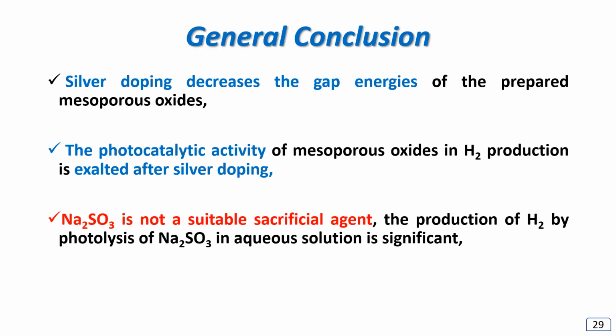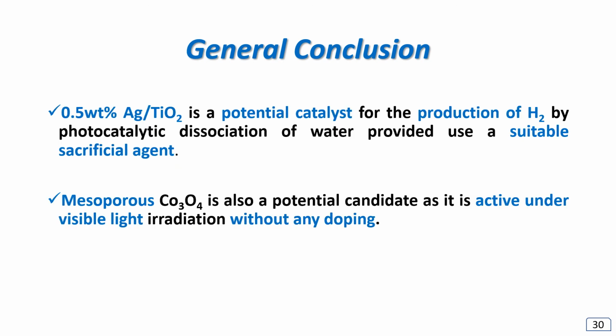In general conclusion, silver doping decreases the gap energies of the prepared mesoporous oxides. The photocatalytic activity of mesoporous oxides in hydrogen production is exalted after silver doping. Na2SO3 is not a suitable sacrificial agent. The production of hydrogen by photolysis of Na2SO3 in aqueous solution is significant. 0.5% Ag on titania is a potential catalyst for the production of hydrogen by photocatalytic dissociation of water, provided we use a suitable sacrificial agent. Mesoporous Co3O4 is also a potential candidate as it is active under visible light irradiation without any dopant.